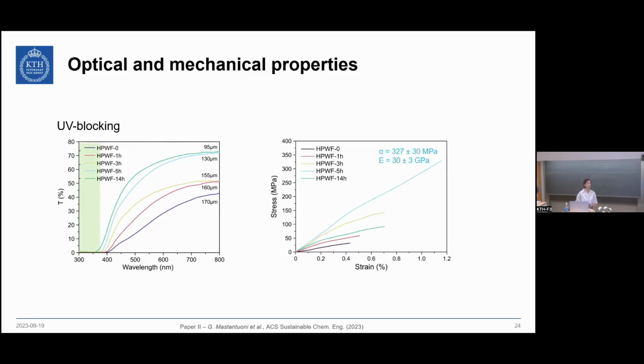A similar trend we could also see from the mechanical properties, which means that we have an increase of both Young's modulus as well as tensile strength the more we push sulfonation time. However, if we push sulfonation too much, so the 14-hour and the green line, then we see again a decrease in both tensile strength as well as Young's modulus. So we can see that there is an optimum level both of sulfonation as well as lignin content.